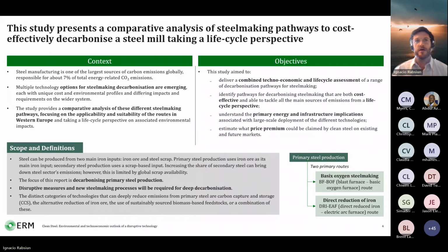the main input. There is a huge role for secondary production in decarbonization because it has a much lower energy and CO2 intensity. But the issue is that the growth of secondary production is constrained by the availability of scrap, and more scrap will become available only with time. So decarbonizing primary production is an imperative, and that's why this report focuses on the decarbonization of primary production. We are not touching on the alternatives for secondary steel production decarbonization that are more related to the procurement of renewable electricity.